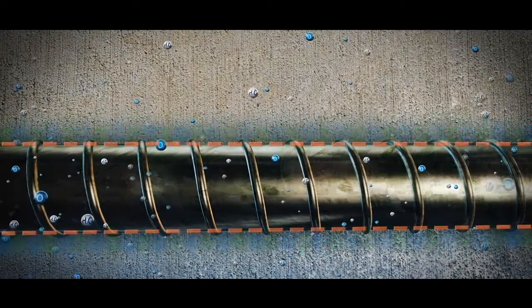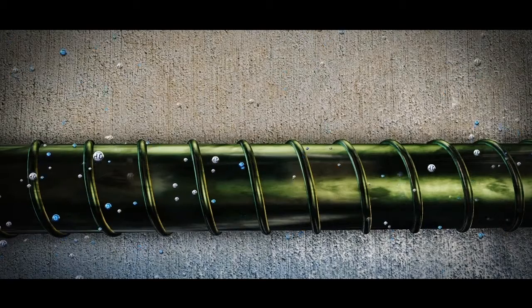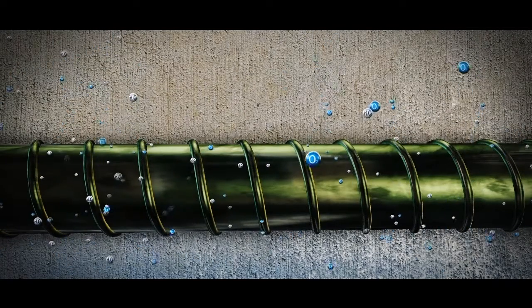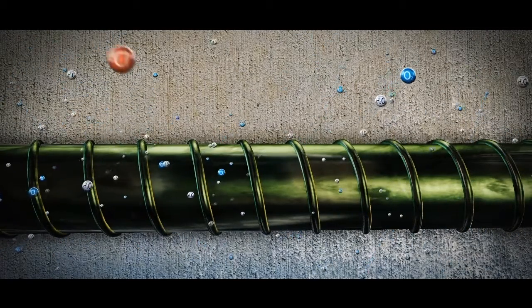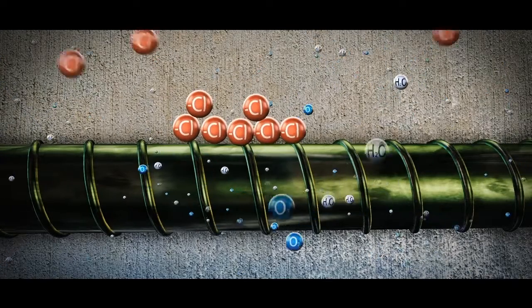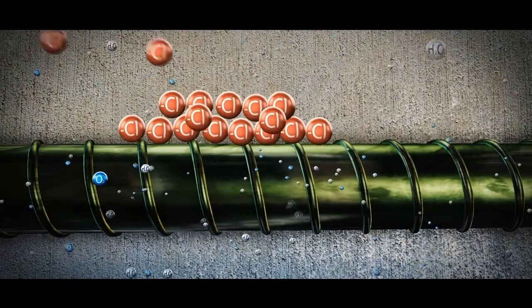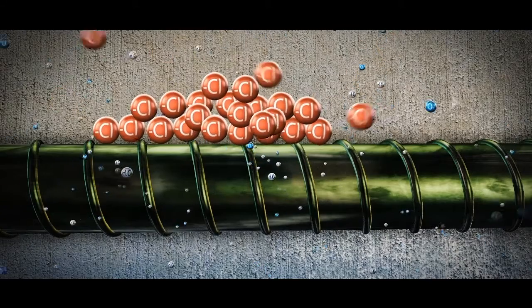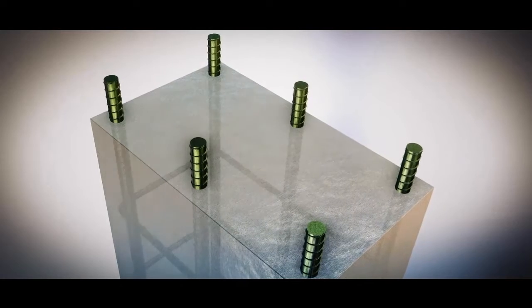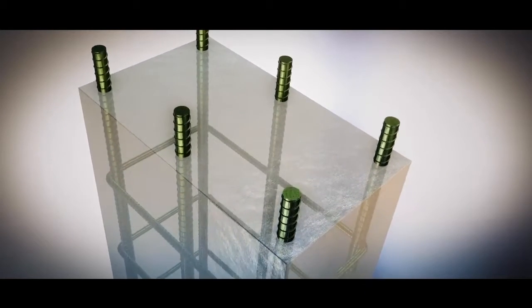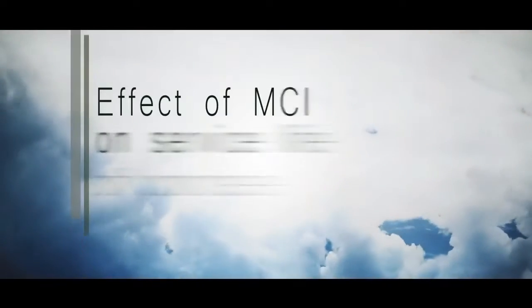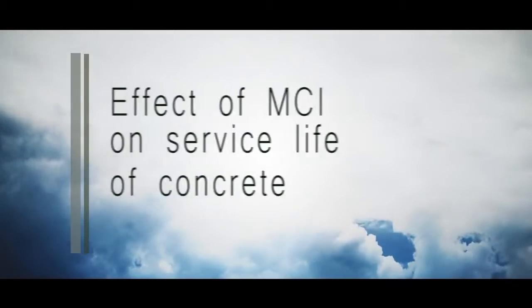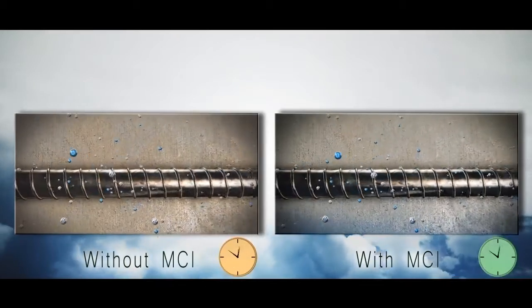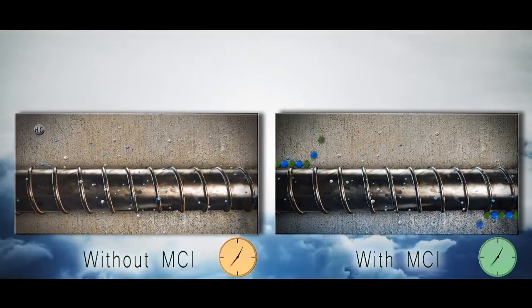Besides protecting steel from oxidation in the presence of moisture, it is much more resistant to the buildup of chlorides. MCI raises the chloride threshold more than 3 times that of uninhibited concrete, so much more chlorides are required for corrosion initiation. When corrosion is initiated, the corrosion rate is significantly lower, thus enhancing the durability of concrete structures and extending their service life.